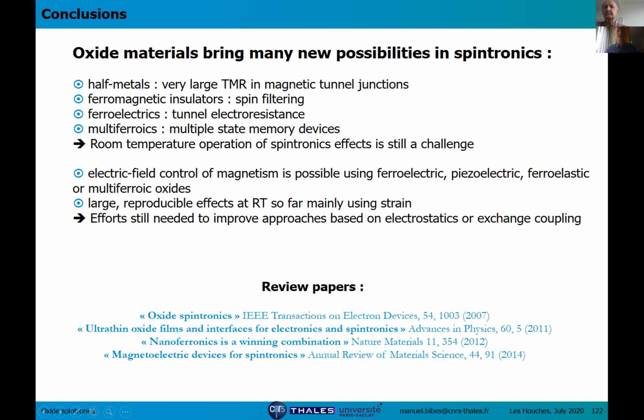Okay, so I'm reaching my conclusion. So this was about oxide spintronics. So hopefully I've shown you that oxide materials can bring new possibilities in spintronics. With half metals such as manganites, you can reach very high TMR. This very high spin polarization also can be used to gain insight into the spin-dependent density of states of a counter electrode. I've shown you results with LSMO, but you can also do it with cobalt, for instance.